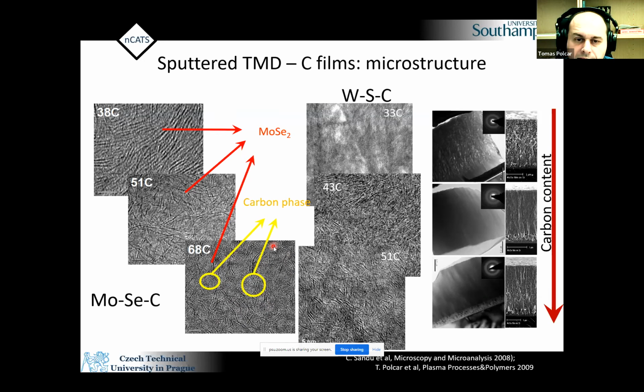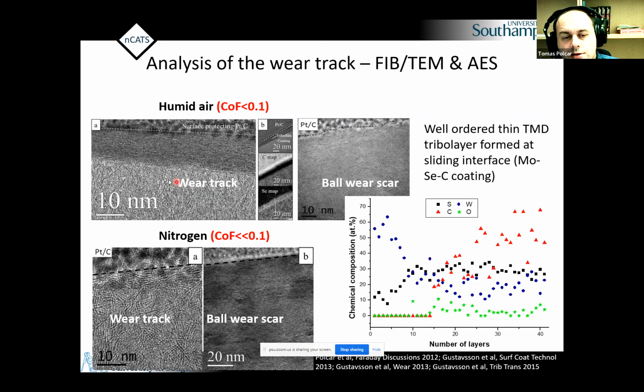We basically do sliding experiments. And that's what we did. And we observed quite an interesting feature. So you have this complex material, as you can see here, which is carbon combined with, in this case, for example, molybdenum diselenide. But after sliding, if you look at the sliding interface, this is where you really slide your counterpart, and you do detail of this point, you will realize that it's almost pure molybdenum diselenide.